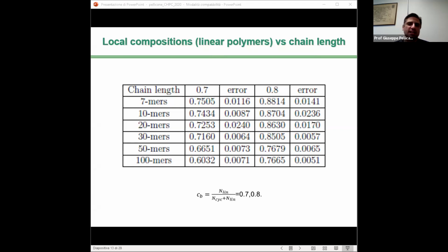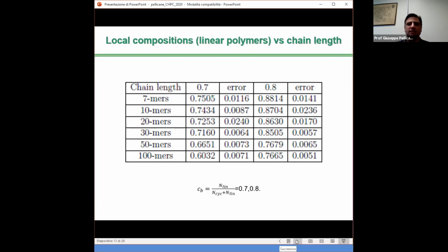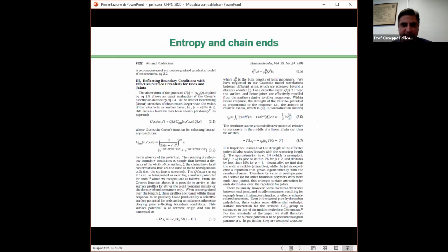The threshold chain length separating enhancement of linear versus cyclic chains is located between 30 to 50 beads per polymer, in agreement with what we found in the case of low cyclic compositions. In the case of polystyrene, that corresponds to a molecular weight of roughly 6,000 to 10,000 grams per mole. Also, this prediction for the threshold is in agreement with the recent experiments conducted on polystyrene polymers. And now we can try to have more insight into this behavior by looking at some quantities in the next few slides.